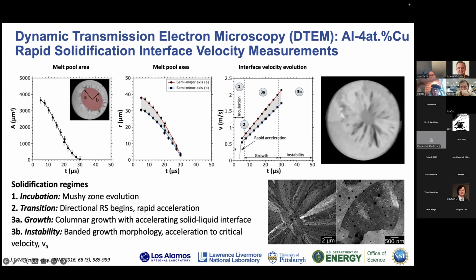So this is solidification velocity versus time. And here you can see some different growth regimes. In this case, we have an incubation region, and then we have a directional rapid solidification. And when we hit about 2 meters per second, so this is very high velocities for solidification, we actually end up having a banded growth morphology in the central region of the melt pool, where those highest velocities are experienced.